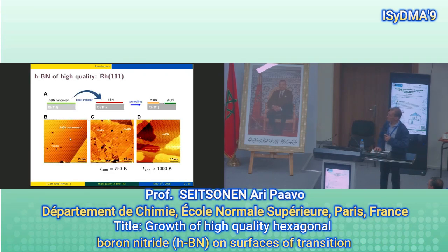So this is the original structure. It's the same as I showed before. It's hBN on rhodium-111, and that's the initial state. Then they detach it from the surface and put it onto some other substrate. Here they just demonstrate it by putting it back on the rhodium, but nowadays they can put it on different substrates.